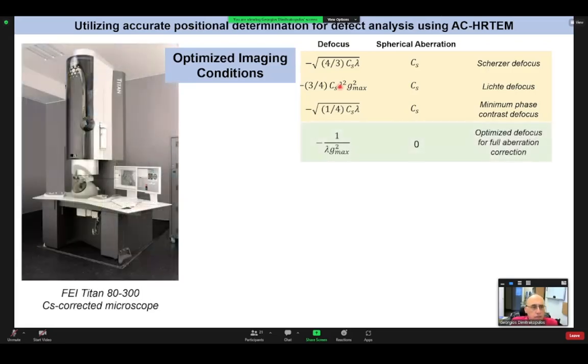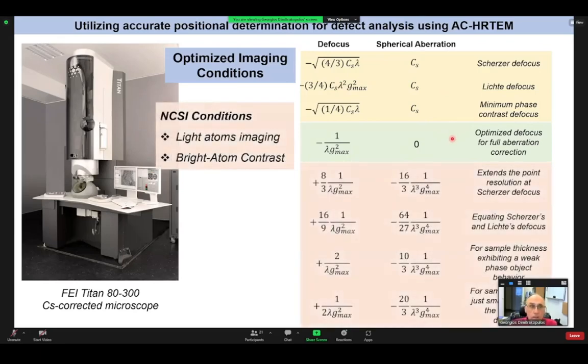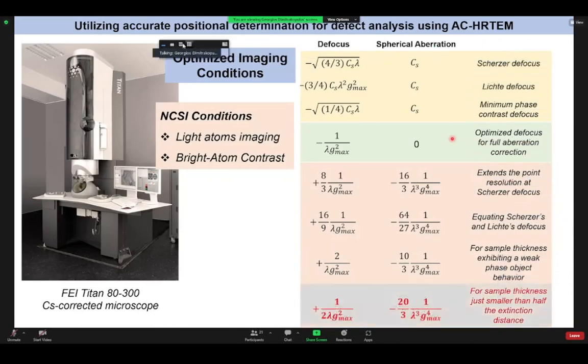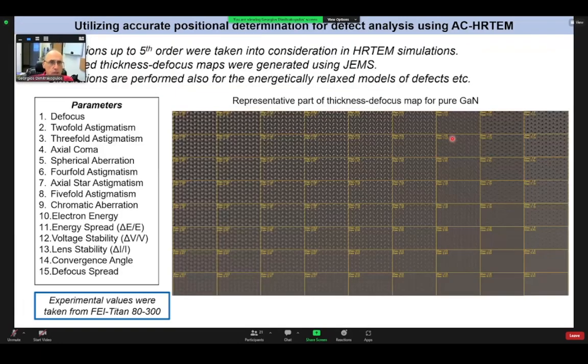Of course, nowadays we have aberration correction, so the spherical aberration is 0, and so you can use 0 spherical aberration, or you can use negative spherical aberration conditions, which under some circumstances you can use, for example, to show the light atoms like nitrogen in gallium nitride, which is not straightforward to see in aberration corrected microscopy. So we have used such conditions.